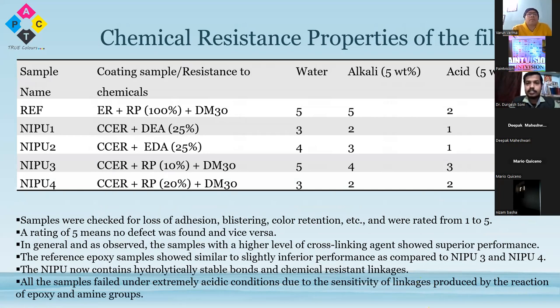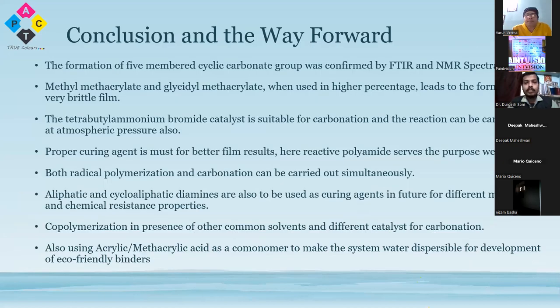This is the result of chemical resistance properties. This is the reference one, and this is the one in which reactive polyamide was used. So almost we can see water resistance was somewhat slightly poorer than the reference sample, and alkali resistance was also good for reactive polyamide 10% and DM30. So at a rating of 5, no such defect was found. Acid resistance was comparatively poor for some of the samples. So these are basically all my trials which were performed during my work.